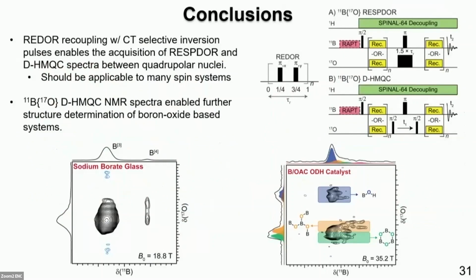So today I showed you how we are using rotational echo double resonance recoupling with central transition selective pi pulses to enable the acquisition of these dipolar-based RESPDOR and HMQC type experiments. And we anticipate that this should be generally applicable to many different types of spin systems. I lastly showed you how we can utilize these heteronuclear correlation experiments to further determine structure within materials of interest, such as this sodium borate glass and this boron oxidative dehydrogenation catalyst.